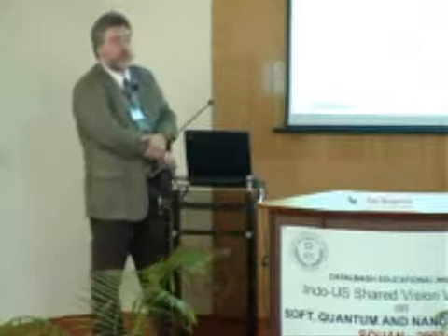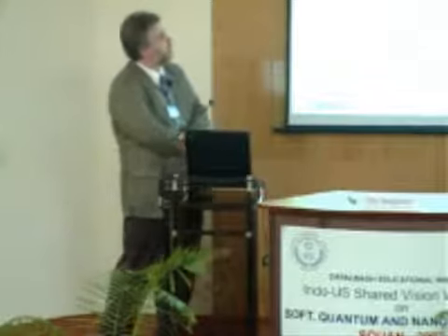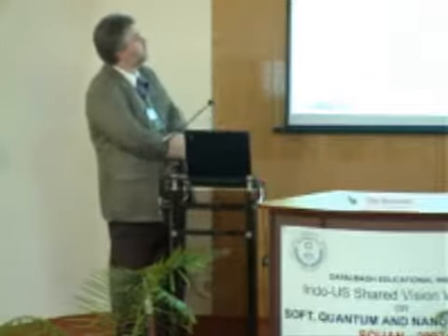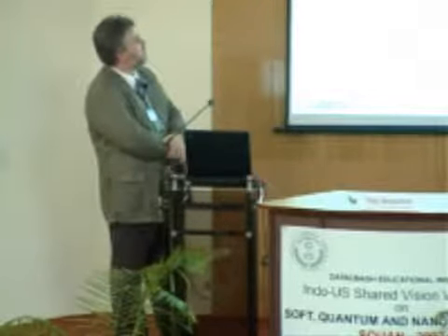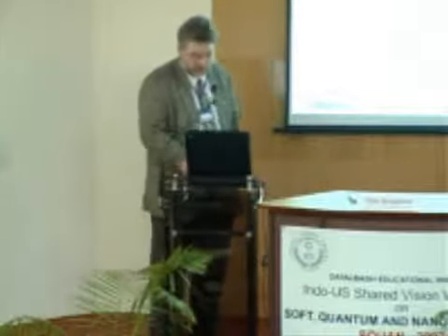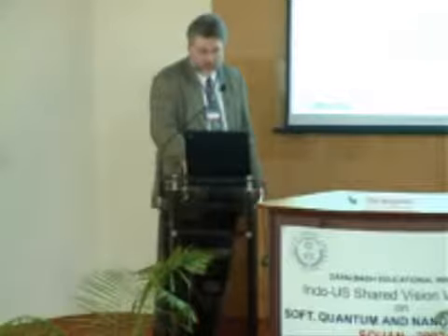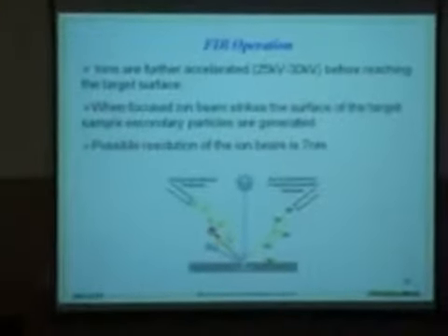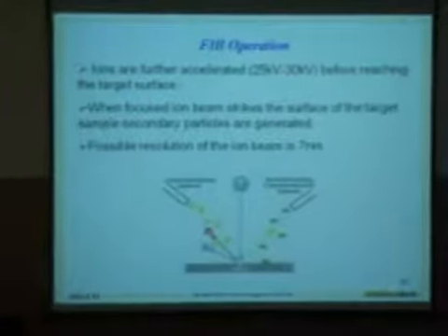Focused ion beam tools basically are configured as scanning electron microscope systems are. You have a liquid metal ion source instead of an electron source that is extracted from the source through a high field. It's focused through a set of lenses down onto the sample. The beam sizes can be as small as 7 or 5 nanometers, which is a little bit larger than that for an electron beam because of the mass of the ions. Typically gallium is used as an ion source. They're accelerated on the order of 25 to 30 kilovolts before they reach the target surface.